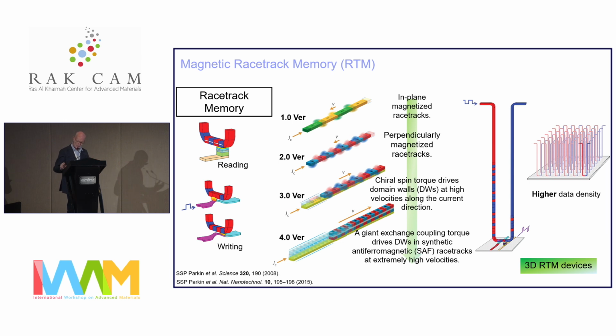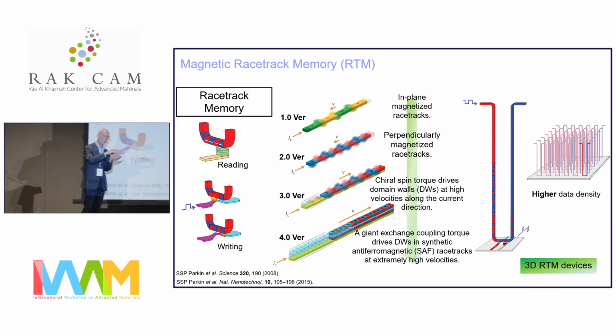Now, the most interesting version is version 4.0. On the magnetic nanoscale, all little magnets, as you know, have stray fields, and those stray fields will cause interactions. For example, if you have a magnetic heterostructure with two layers, one on top of the other, on the nanoscale, if the layers are magnetized parallel, they will automatically become antiparallel through these stray fields. On the other hand, if they're magnetized perpendicular, they will automatically be organized in a parallel fashion. So you have to avoid these stray fields.